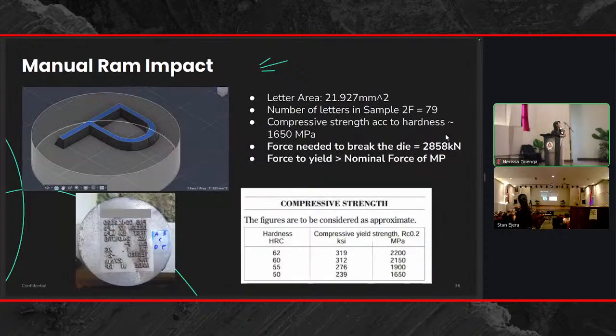And further emulating it in software, we calculated the force, the theoretical force needed to break the die, which is about 2858 kilonewtons. This was based on the lowest hardness value that we measured earlier, which was about 53 for sample 2F. So even then, we saw, parang hindi siya abot, hindi umabot yung theoretical force to break the die. So for now, theoretically, we can say at least na parang yung manual ram impact, hindi siya yung predominant cause of failure.